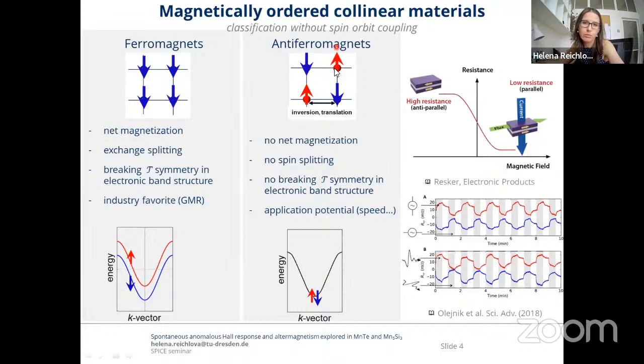One can also see it from here: when the spin is flipped, then translated by half unit cell, the original unit cell is recovered, and the time reversal symmetry is not broken. Despite all these seemingly disadvantages, antiferromagnets are attracting a lot of attention lately. And they also have clear application potential. So one of the things which we like about antiferromagnets, beside the absence of the stray field and so on, is the speed of the reversal. They can be reversed faster than the ferromagnetic materials, as was shown, for example, by Kamil Olejník in this publication when the antiferromagnet was switched by terahertz pulses.